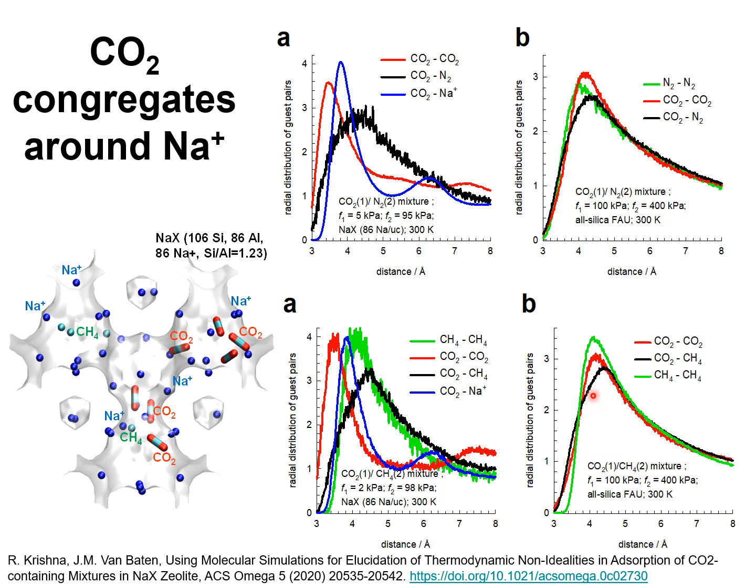The distances between any of the pairs, CO2-CO2 pair or CO2 methane pair or methane-methane pair, is practically the same. Introduction of extra framework cations leads to congregation of CO2 around those cations, and for both these mixtures, the partner molecules, nitrogen in this case and methane in this case, have to incur less severe competition with CO2 for mixture adsorption. And this explains the reason that the IAST, which presumes or assumes a uniform distribution of adsorbates, overestimates the adsorption selectivity.